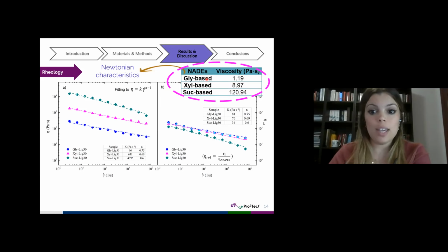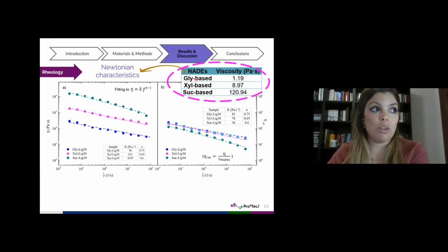In this way, sucrose, which contains the higher number of hydroxyl groups, reveals the highest viscosity value due to the sucrose chemical structure, whilst the other ones show very low viscosity values. Thus, the more hydroxyl groups that are available to react with the carboxylic group of citric acid, the more hydrogen bonds are formed, leading to an increase in viscosity.